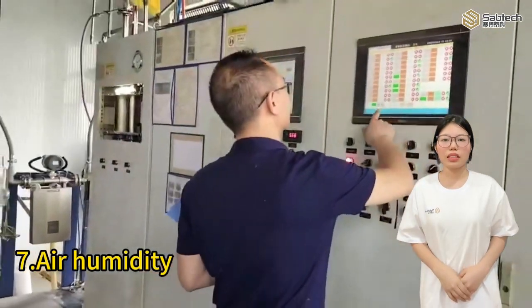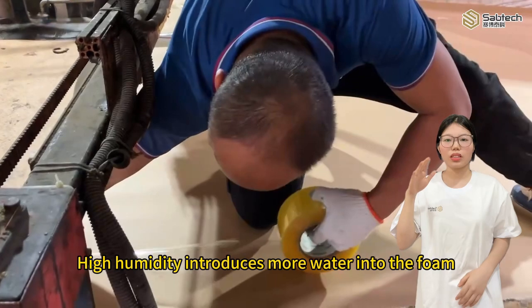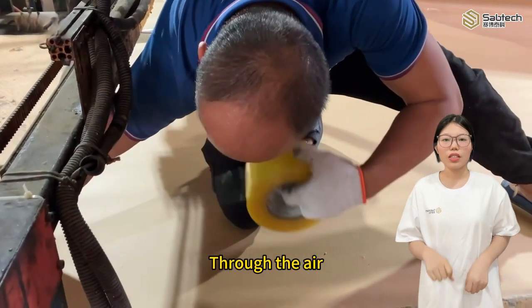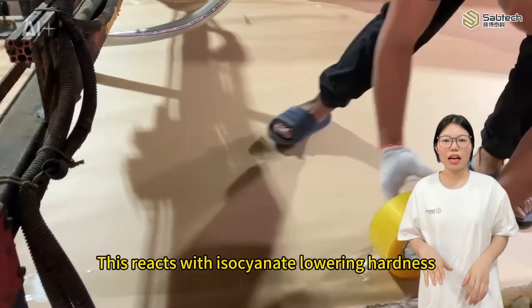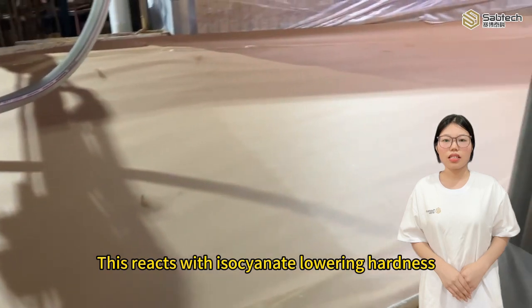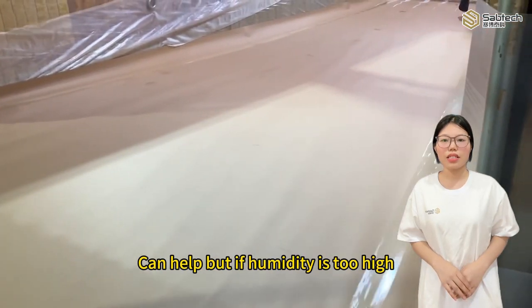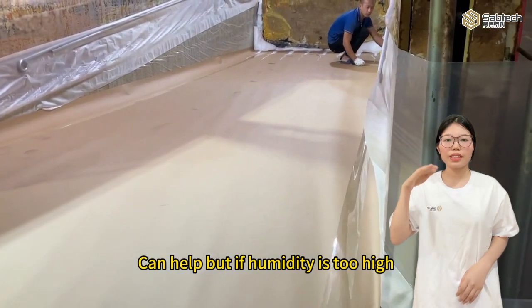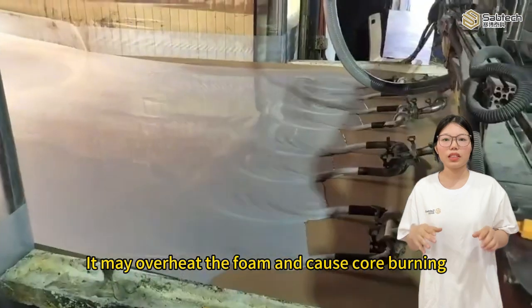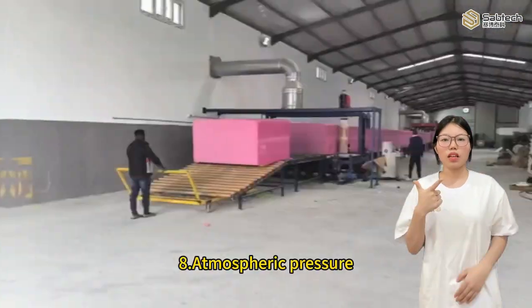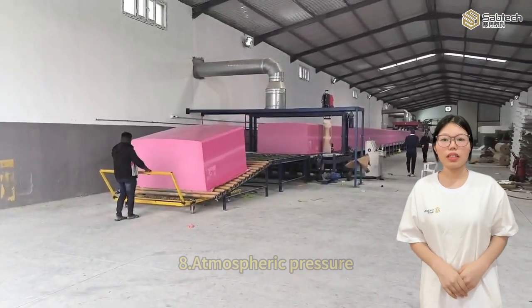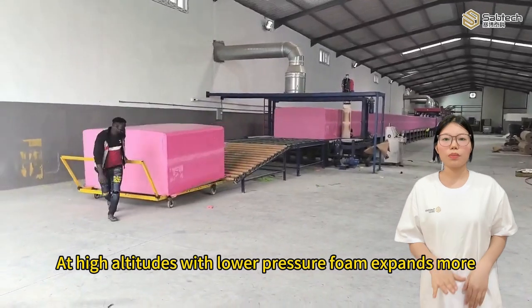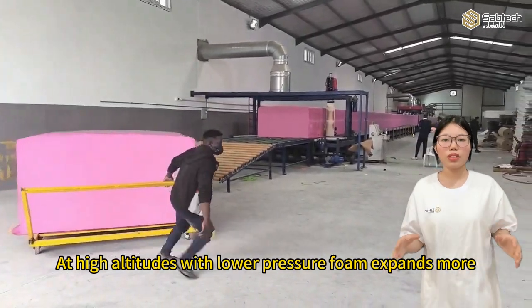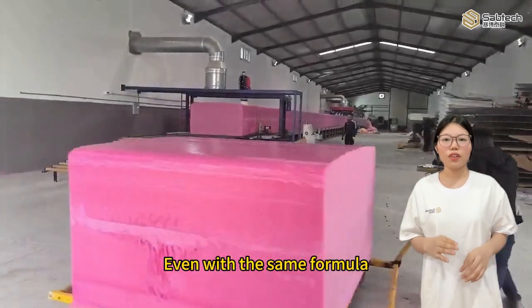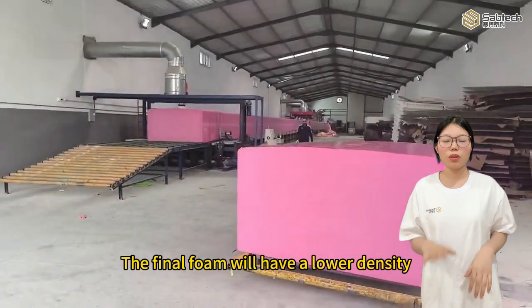Seventh, air humidity. High humidity introduces more water into the foam through the air. This reacts with isocyanate, lowering hardness. Slightly increasing TDI can help, but if humidity is too high, it may overheat the foam and cause core burning. Eighth, atmospheric pressure. At high altitudes with lower pressure, foam expands more. Even with the same formula, the final foam will have a lower density.